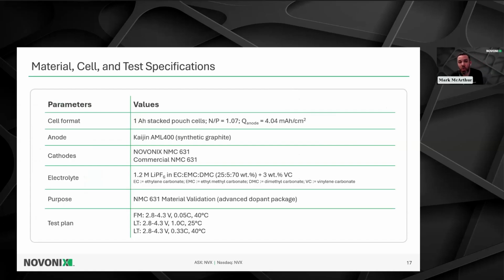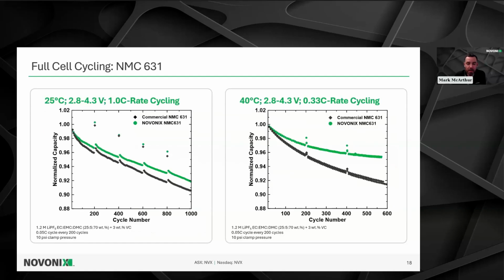But we don't end in just simple coin cell measurements. We do have the ability through our Battery Technology Solutions division to construct our own pouch cells. In this case, I'm illustrating 1 amp hour stacked pouch cells, which were made using either the NOVONIX NMC 631 material or that commercial NMC 631 material. And we are pairing that against a well-known synthetic graphite called AML 400. And we're performing a few different test protocols on each of those cell types. Those types of measurements I mentioned earlier are either 25-degree cycling data at 1C rate or higher temperature 40-degree cycling at 0.33 C or C/3 rate.